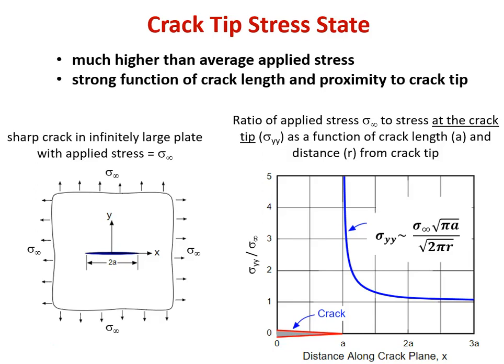Just like a stress intensity factor from a hole or a macro design defect, or not a defect, excuse me, a design feature, the stress state at the crack tip is much, much higher than the average applied stress. And in fact, it's much higher even than a geometric discontinuity like a through hole, rivet hole, or a section thickness change. It's even bigger. It's a strong function of crack length and the proximity to the crack tip.